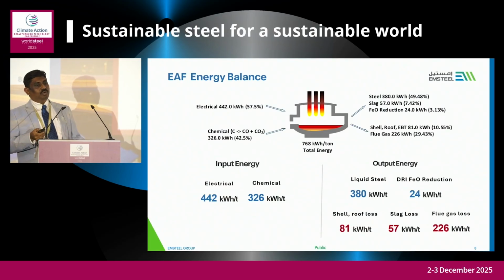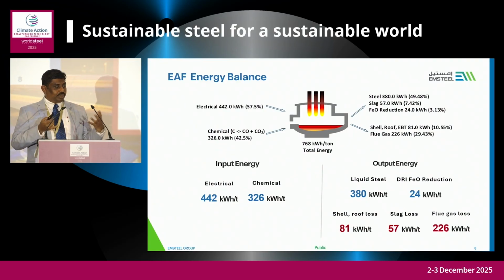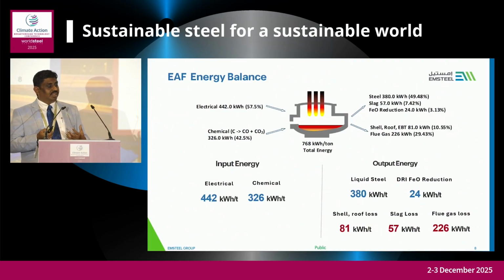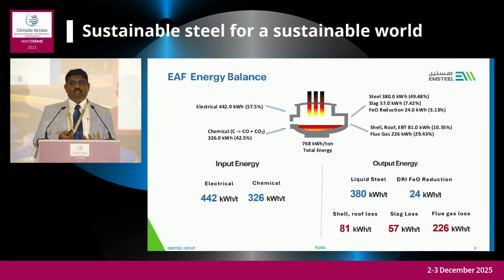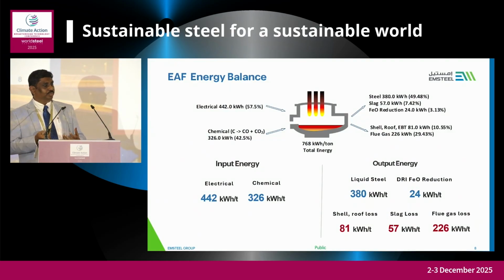We have also done the mass and energy balance calculation. This is based on our furnace, but maintaining some DRI temperature and carbon, because DRI temperature and carbon are linked. If you want to optimize the DRI by increasing the carbon, your DRI temperature goes down. So there is a multi-objective optimization we need to work on here, where we have to optimize both DRI carbon and DRI temperature.